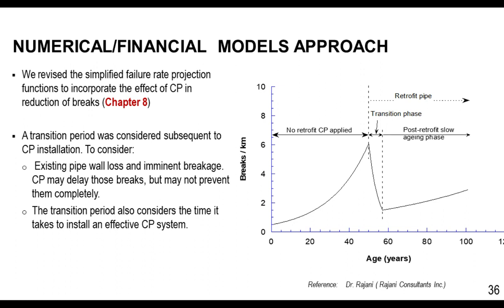And we call that the post-retrofit slow aging process. So what is the reason for considering a transition period for CP? The reason is that before installation of a cathodic protection, an existing pipe may already be corroded and has a significant wall loss, and there is some imminent breakage. So the cathodic protection may delay those breaks, but may not completely prevent them.